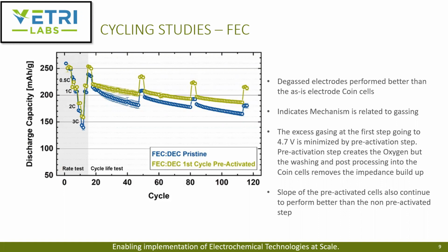You can see that the slope of the pre-activated cells also goes down, but it is at a much better slope compared to where the activation was done in the coin cells, where the decomposition products and gassing had no chance of being removed. So the gases and decomposition products end up increasing the impedance of the cell, whereas with the pouch cells, where they could degas electrodes and wash them, you can obviously remove the impedance-causing products and mechanism. That's what this shows.